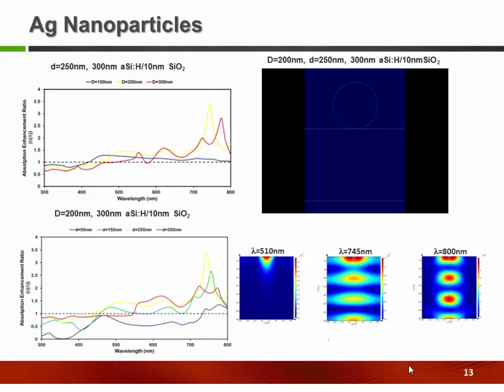And it normally depends on the plasmonic frequency of the metal. Above that frequency, we could normally obtain good performance in different metallic structures. For example, here, the size of the silver nanoparticle increases, and we see that for the optimum size, which is around 200 nanometers in diameter of the silver nanoparticle, we have seen the best performance.